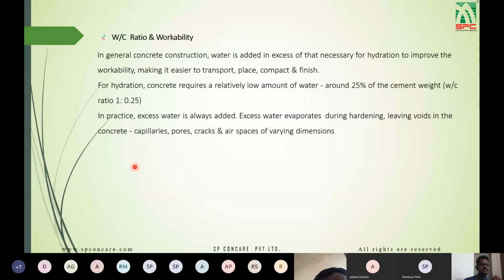As I said, in the hydration reaction, you need water to complete the reaction. But how much? For that, the water cement ratio comes in. So what is the water cement ratio? Water cement ratio is kg of water per kg of cement. This water cement ratio is mostly around 0.25 to 0.3. So what is 0.25? Suppose you have taken 100 kg of cement. As per the water cement ratio, around 25 liters to 30 liters of water is sufficient for that.